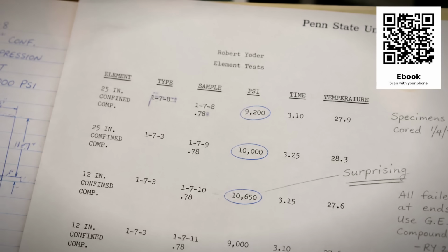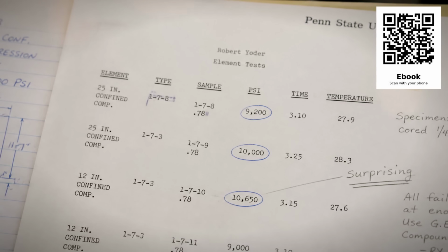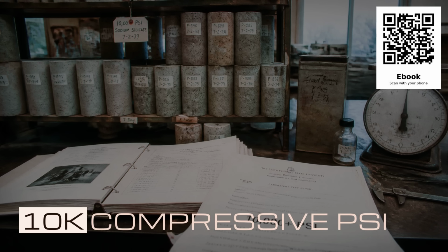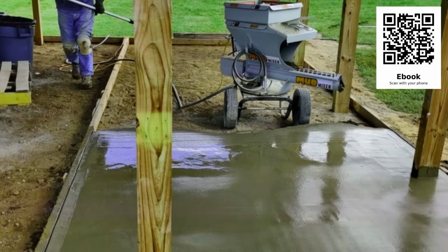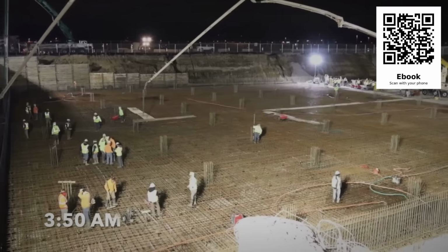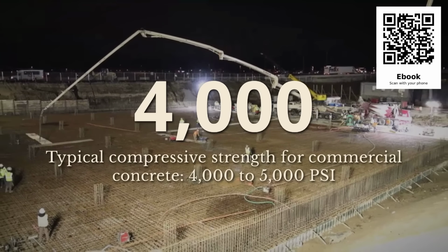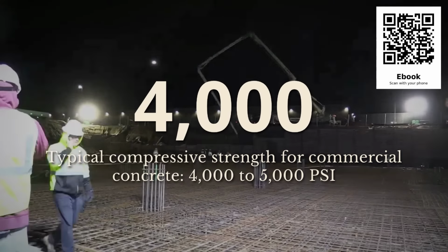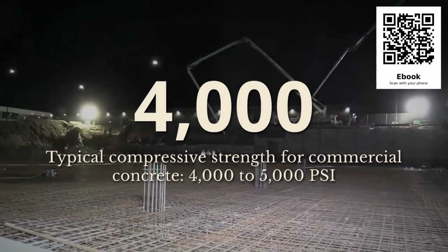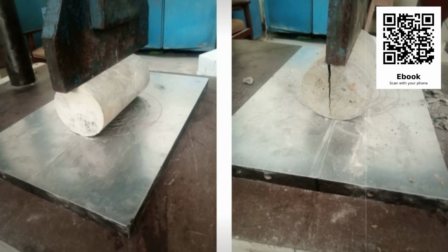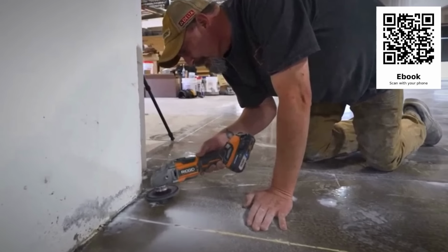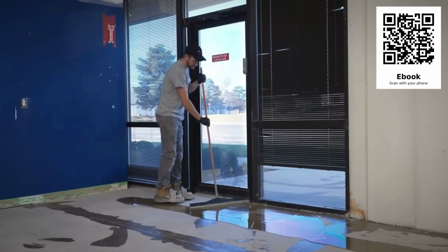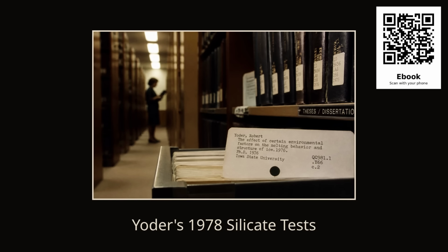The numbers he got were, in his own words, surprising. Some of his samples reached over 10,000 psi after a year of curing. By comparison, standard residential concrete is rated at 3,000 psi, and commercial concrete is typically 4,000 to 5,000 psi. The silicate sand was, in some cases, more than twice as strong as the concrete it would have replaced. Yoder's thesis was filed in the Penn State Library. It was never published in a peer-reviewed journal.